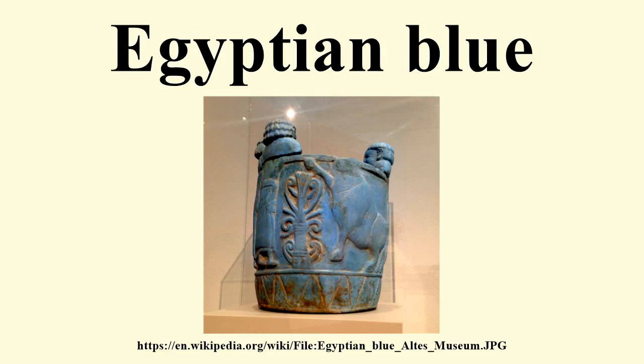Egyptian blue consists of rectangular blue crystals together with unreacted quartz and some glass. From the analysis of a number of samples from Egypt and elsewhere, the weight percentage of the materials used to obtain Egyptian blue in antiquity was determined to usually range within these amounts: 60 to 70% silica, 7 to 15% calcium oxide, 10 to 20% copper oxide. To obtain theoretical cuprorivaite, where only blue crystals occur, with no excess of unreacted quartz or formation of glass, these percentages would need to be used: 64% silica, 15% calcium oxide, 21% copper oxide. However, none of the analyzed samples from antiquity was made of this definitive composition, as all had excesses of silica, together with an excess of either CuO or CaO.